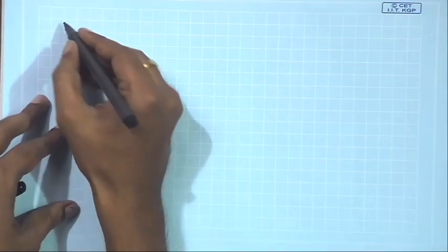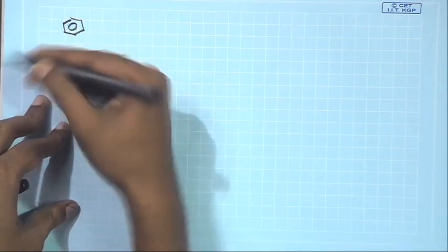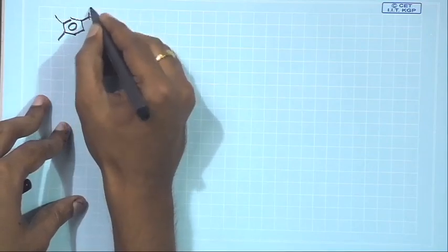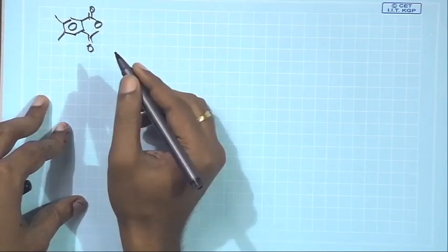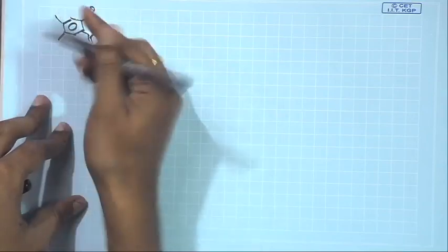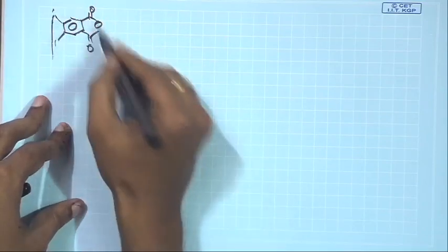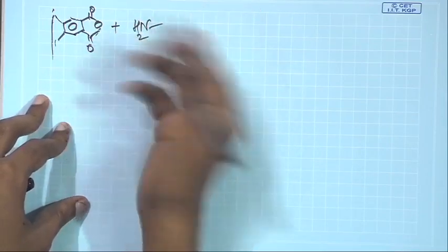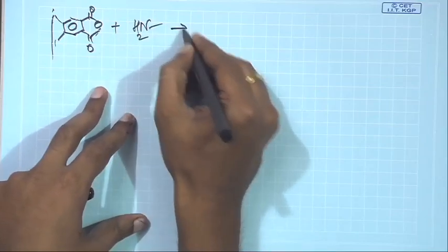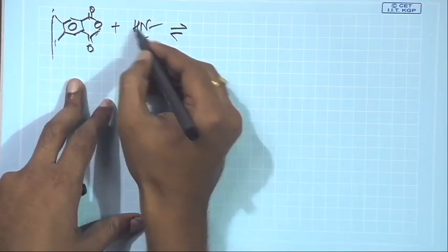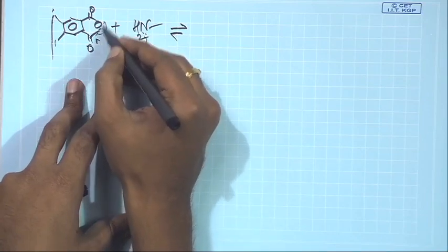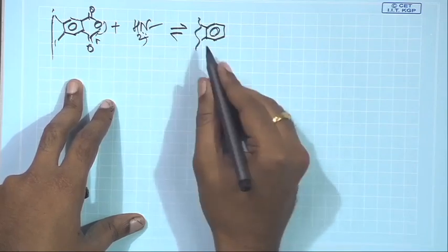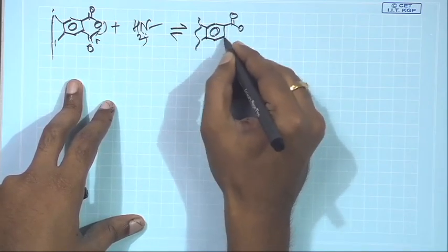Let us have a closer look at the polyamic acid synthesis. I will draw generically one side of the ring, because it is pyromellitic dianhydride. So, this side of the dianhydride is there; I am not drawing the other anhydride. You have an anhydride here and one amine from the diamine that I am showing. Let us look at the mechanism in a little more detail. The first step is that this amine will attack here and this ring will open. What will be the product that will form? The product will be something like this.